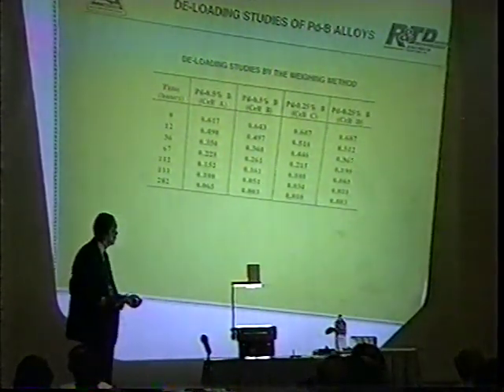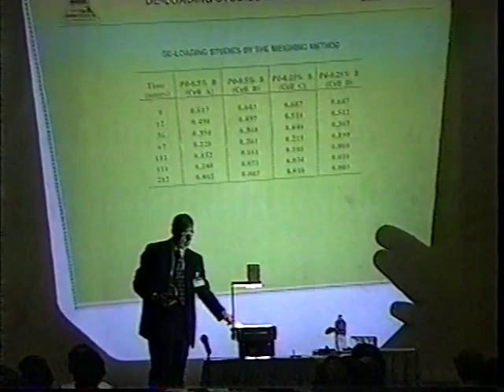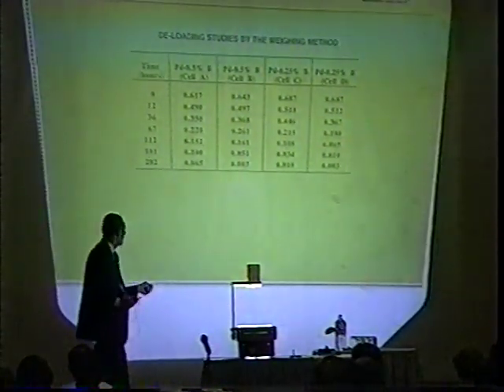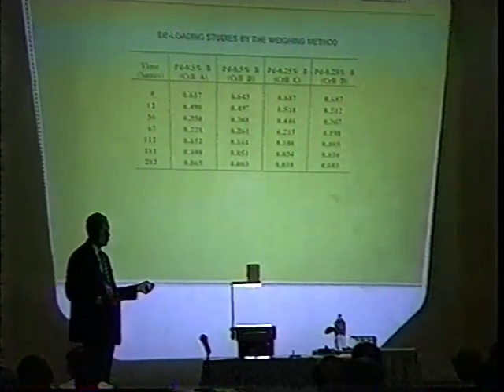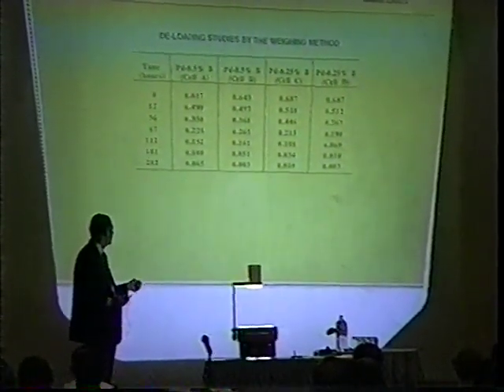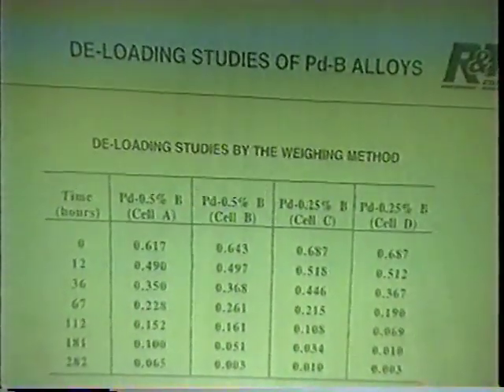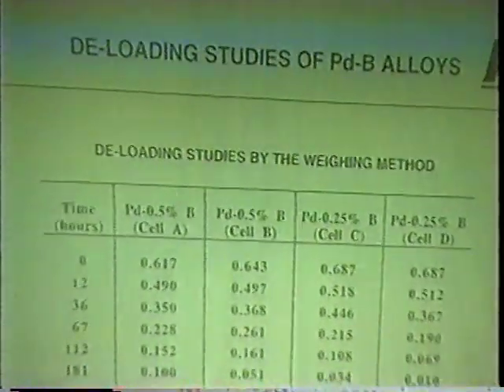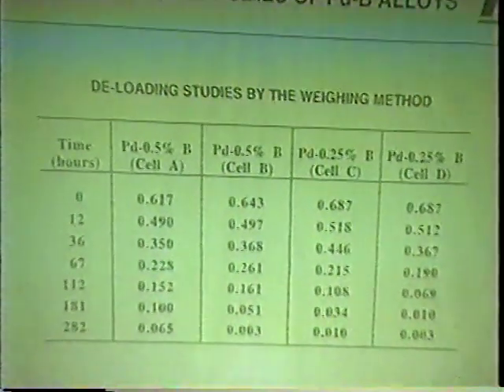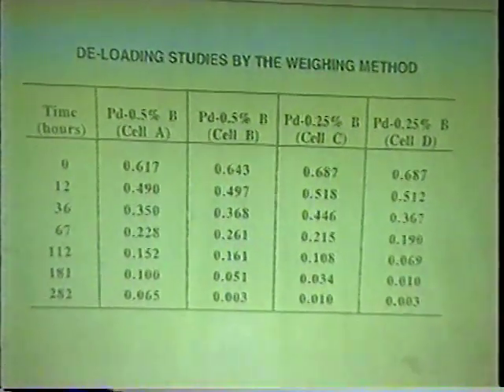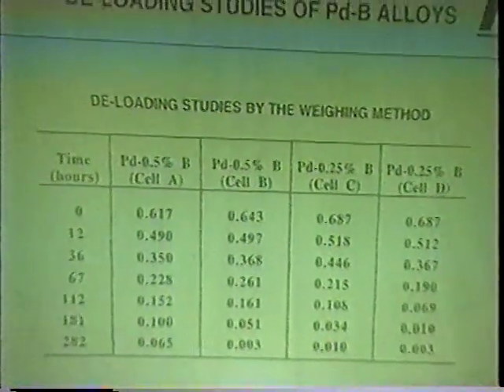So you could measure the loading by this method to the third decimal place. I'm surprised with that. You get quite an accurate value. And for the palladium boron alloys, of course, the smaller percent boron, you would get higher loading, as you see right here. But the main thing is the deloading. The deloading is very, very slow. If I take out a solution over a 10-minute period, there'd be practically no weight gain. It would only change by 0.001 in a 10-minute period.